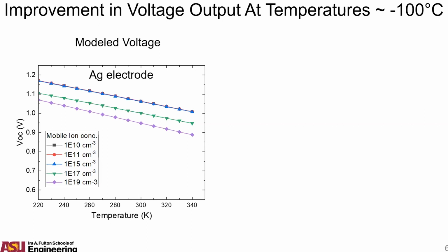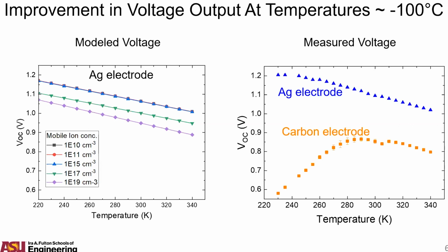Now this is just going down to just around -100 Celsius. But this trend is something we have to explore at even lower temperatures, towards lunar night temperatures, and how these hold up. But we were able to confirm that with a certain configuration of our devices using silver electrodes, we can match the same type of behavior as our model, and that we have low mobile ion concentrations. You don't want to have ions moving around in a PV device.